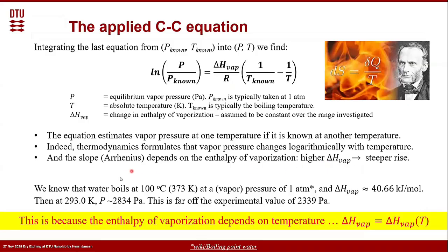Again, let's take the example water. We know it boils at 100 degrees at a vapor pressure of 1 atmosphere. And we also know that the enthalpy of vaporization is 40.66 kilojoule per mole. Then at 20 degrees, now we can calculate that the vapor pressure is 2,834 Pascal. Well, this is far off from the number we just saw, 2,339 Pascal. Much worse in this case than, let's say, our fitting technique.